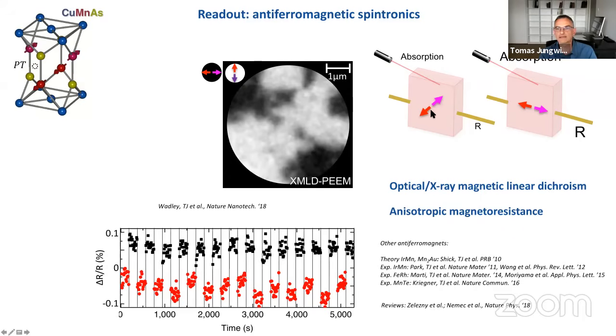So we can detect then, for example, the reorientation of the magnetic order from a direction orthogonal to the probing current to the direction parallel to the probing current, and what we will see is a change in the resistivity of the material. And these are real experimental data where we see that we reorient the Néel vector or the antiferromagnetic moments by 90 degrees, and we see these changes in the resistivity or resistance signal due to anisotropic magnetoresistance.